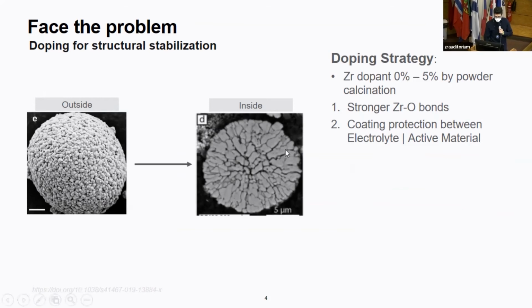The doping strategy we want to use is to dope the material with zirconium in a wide range of concentrations by powder calcination. We want to go for zirconium because we think we could have a double effect. The idea is that if the zirconium is included in the crystal, it will lead to stronger bonds, which will possibly improve the stability. And also we'll have a coating protection between the electrolyte and the active material, which will protect the particle from the electrolyte.